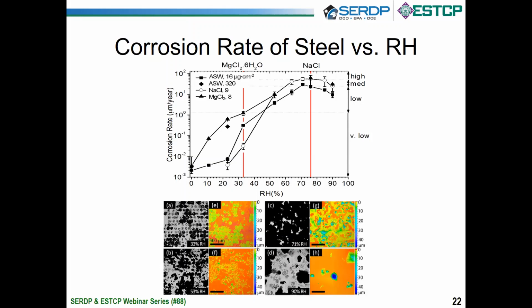And even down to 50%, the amount of corrosion is not negligible. If you look at seawater, even if you drop down to 30 to 35% relative humidity, it's very low, but it's occurring. Part of the reason is that seawater contains magnesium chloride, and that magnesium chloride allows the surface to remain wet, even at very low relative humidity values. So the first point that I want to make is that you can't just say corrosion happens above 80% and doesn't happen below 80%.